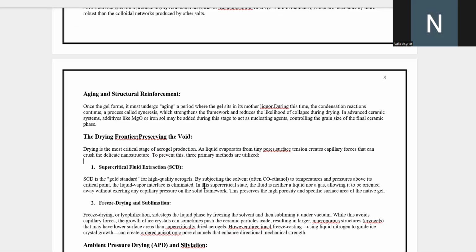These methods are supercritical fluid extraction, freeze drying, and ambient drying. The first is supercritical drying, the gold standard. This method completely avoids the liquid and gas phases. The wet gel is placed in a high-pressure chamber and the liquid, often alcohol or liquid CO2, is heated in a pressurized chamber until it becomes a supercritical fluid, a state where it is neither a true liquid nor a gas. In this form, it can be gently vented away without ever creating a damaging liquid-air boundary. This preserves the gel's original nanostructure perfectly, producing the highest quality aerogels, but it is complex and expensive.